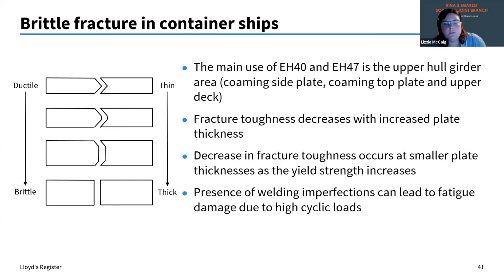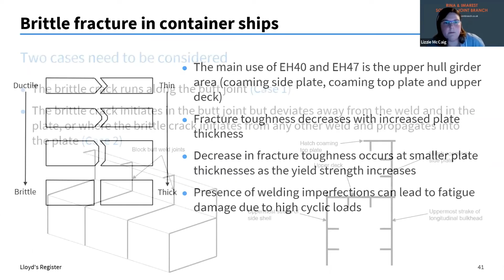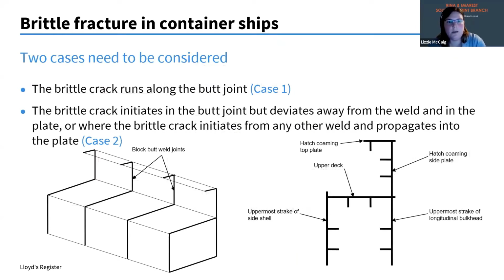So when we think about container ships, IACS have introduced a unified requirement, UR S33, that does look at this problem. In that UR, we consider two cases. We consider the case where you might have a brittle crack running along the butt joint of the block, or even the subblocks. And then also you could have a brittle crack initiating in that joint, but deviating away from the weld and into the plate. Or if you've got other weld attachments like the longitudinal stiffeners, you could have a brittle crack initiate from one of those welds, and that could also propagate into the plate.